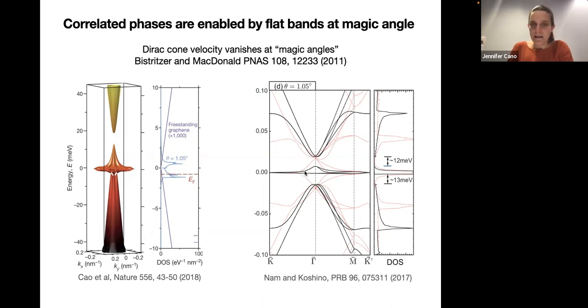And on the right-hand side here, this is showing a more detailed ab initio calculation. So you should look at these black lines, which is for the relaxed atoms. And you see that there's this very flat band with a bandwidth of like 10 meV, which is appearing. So that's the flat band, which is appearing at this magic angle. It's not perfectly flat, but it has a really small bandwidth, and it's separated above and below from the conduction and valence bands. So we can think about this band by itself, and that's where the correlation physics is coming from.